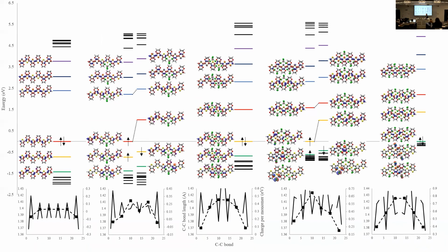So it's interesting. The two are completely separate, right? When you're actually conducting electricity down the polymer, you don't per se get any anionic movement. What the anions do is they introduce these defects, and these defects then overlap slightly. The main thing is that the more anions you add, the band gap gets narrower, and that's what really allows the conduction to take place. You can have much easier promotion of the electrons into the otherwise unoccupied level. That's what allows the conduction. It's mostly by hole conduction actually.